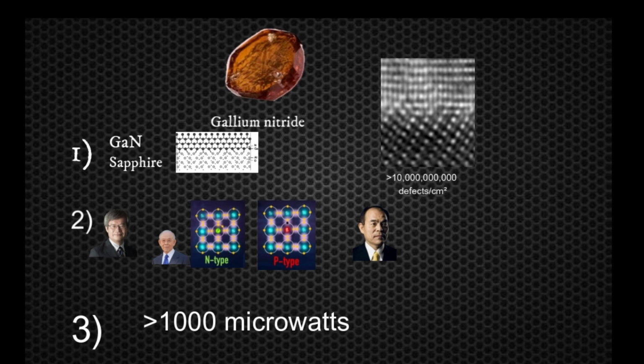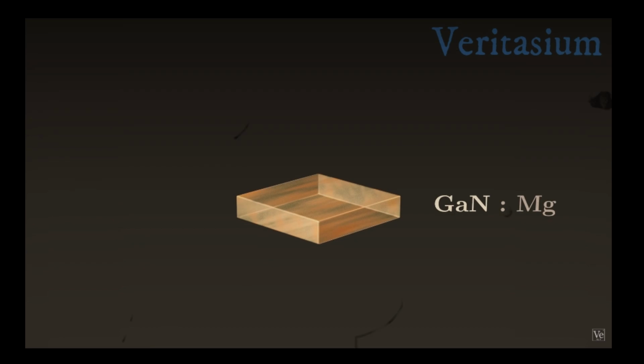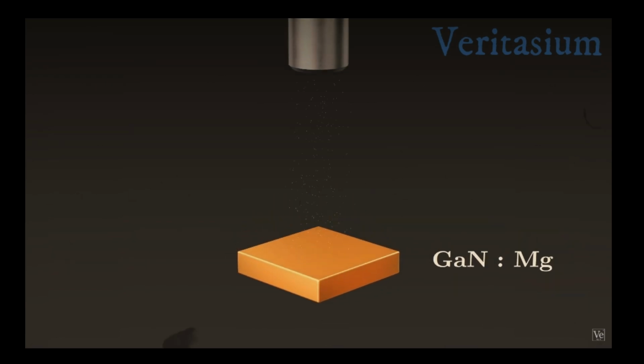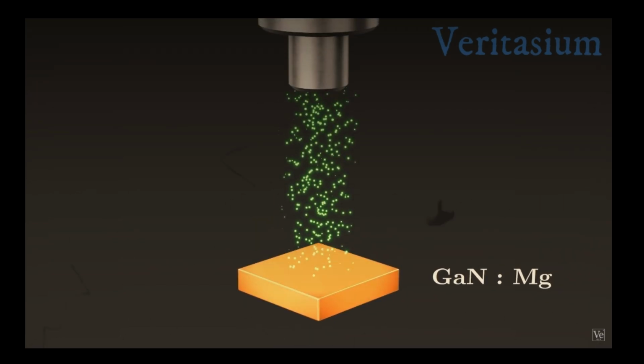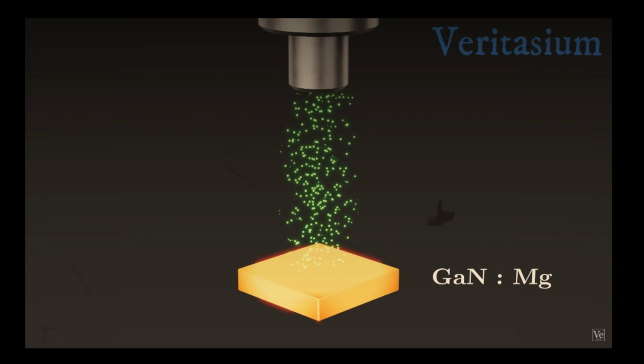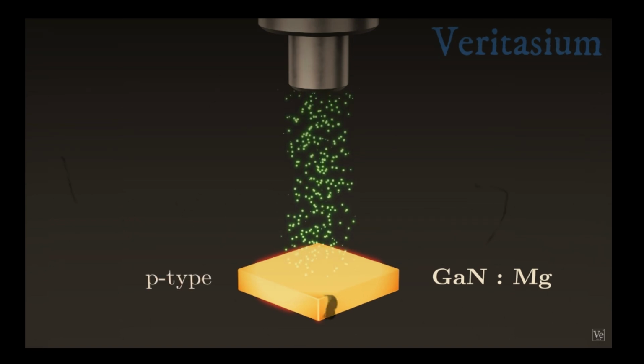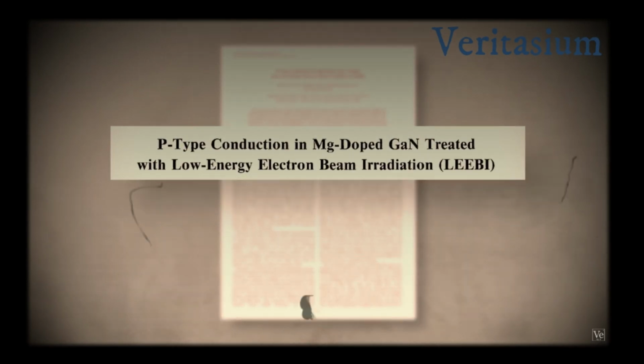Here, Akasaki and Amano had again beaten him to the punch. They had created a gallium nitride sample doped with magnesium, but at first it didn't perform as a P-type as they expected. However, after exposing it to an electron beam, it did behave as a P-type, the world's first P-type gallium nitride, after 20 years of trying.